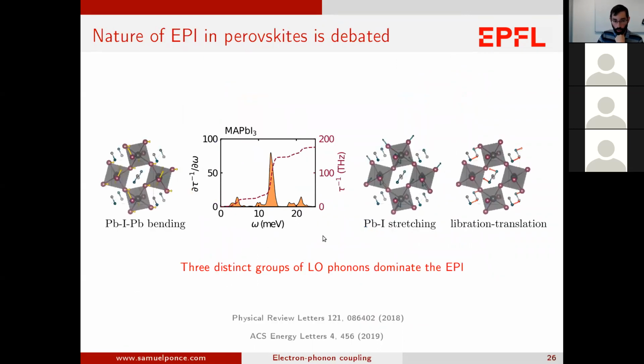And so if we look more closely at what those vibrations are, the first one is a lead iodide bending of the cage. The main one, this big peak around 13 meV, is a lead iodide stretching of the bond. And then the last one is a libration and translation of the molecule. And so, of course, you don't see that peak in the cesium lead iodide because you don't have molecules. And so what we can see is that in MAPI, the electron-phonon coupling is dominated by three distinct groups of LO-phonon modes.